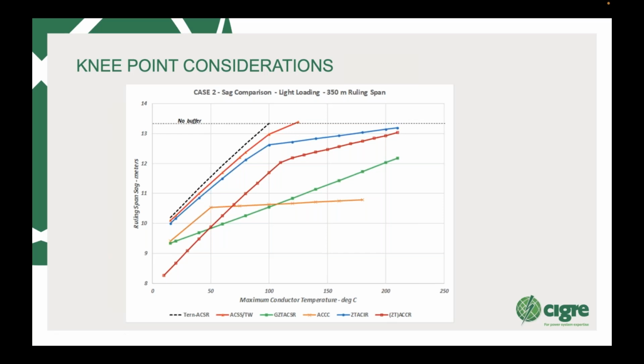So now you want to increase this to get more power down the line, and so therefore you have to have a higher temperature. So you could try, say, the ACSS trapezoidal wire, which will take you up to about 120 degrees, 130 degrees C. So now instead of only pushing down current, which will give you 100, you can now go to 130.